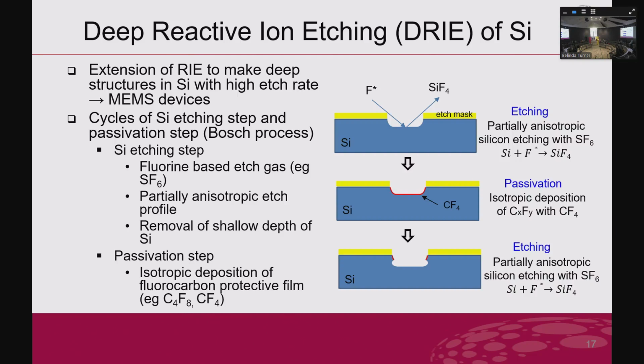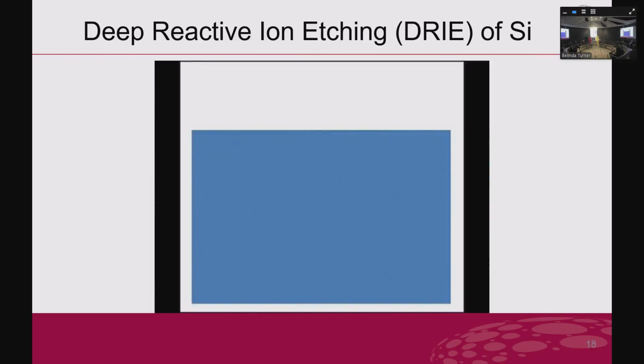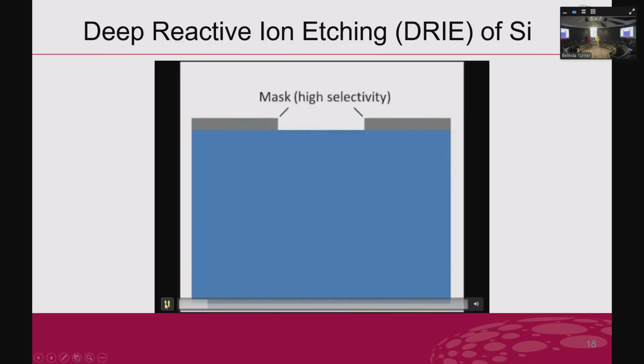So back to the RIE, then they come up with deep RIE, so-called deep reactive ion etching. We call this process the Bosch process. Yes, it was developed by the German company Bosch, and so we call it the Bosch process. So it's a cyclic etching process. Basically, the first step you etch your substrate, then you passivate the etched area with carbon tetrafluoride gas. Then you carry on with the third step, etching. So repeat that process, you can form the deep groove. Then I'll show you the video. So it's a repeat process.